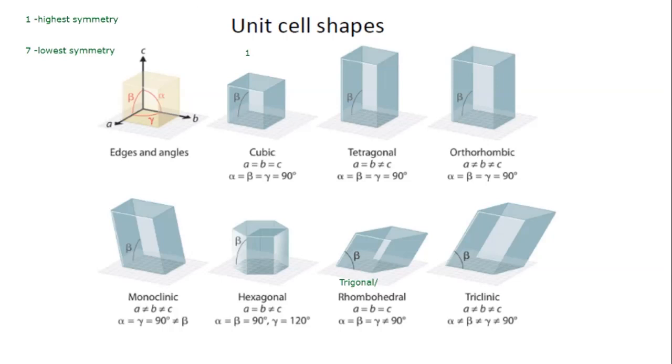Then it would be, similar to maybe, hexagonal, trigonal, tetragonal, orthorhombic, monoclinic, and triclinic. So cubic is the highest symmetry crystal system, meaning it has the most symmetry elements. Triclinic is the lowest symmetry, meaning it has the fewest symmetry elements. In fact, in triclinic, there's only one symmetry element in either of the triclinic space groups.